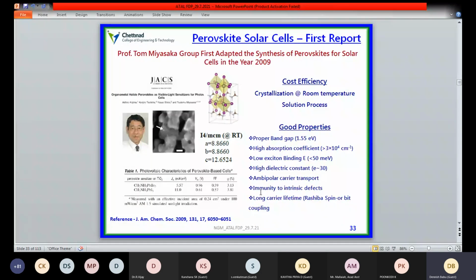So this is the first report published by the Miyasaka group, and it is mentioned here that they achieved only 3 percent power conversion efficiency. At that time, it was identified as important because they have excellent properties, especially for optoelectronic device applications. They have a proper bandgap value around 1.55 electron volt, high absorption coefficients, low exciton binding energy, high dielectric constant, good charge carrier transport, immunity to intrinsic defects, and long carrier lifetime, which is considered an important property for optoelectronic devices.